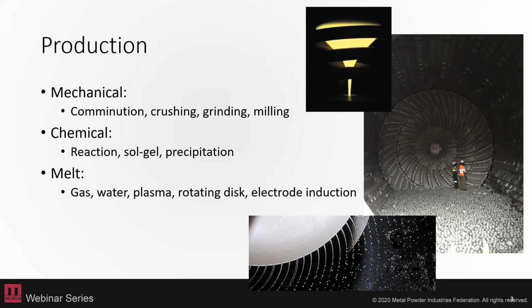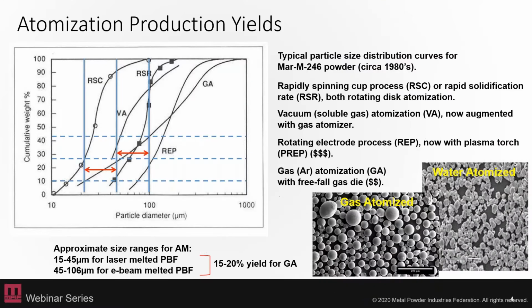There are mechanical methods of producing powders, including crushing and grinding and milling to produce those powders. There are chemical methods such as reaction pathways, sol gel methods, or precipitation of ions from a fluid onto a substrate, or through electrolysis. There's also melt methods of powder production, such as gas atomization, water atomization, plasma atomization, rotating disk atomization, and electrode induction melting with atomization capability. So the method that you use to produce your powder is going to have a significant effect on the powder that is produced.